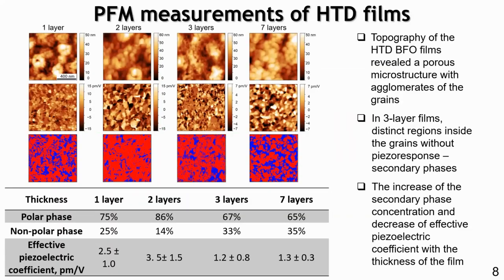As you see in this image, these are representative images of the films with a different number of layers. You can see that the morphology of the film in the top row of the images is not really perfect. We have small grains collected in agglomerates, and we have some pores inside the films. Even with increasing thickness of the film, the pores become a bit smaller, but nevertheless they still remain in the films. And this actually makes sense.